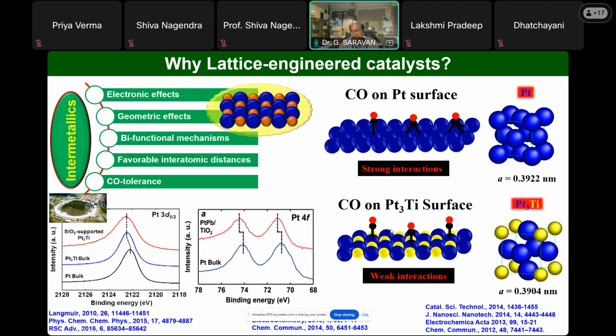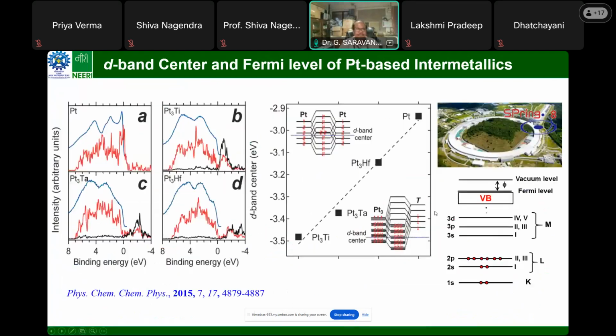So you need to spend a little energy compared to pure platinum to achieve the target reactions. This is because the intermetallic phase has structural benefits. We have calculated the d-band center of various materials, and compared to platinum, the d-band center is entirely different, which is favorable for the target application. This is the story for most automobile exhaust applications.